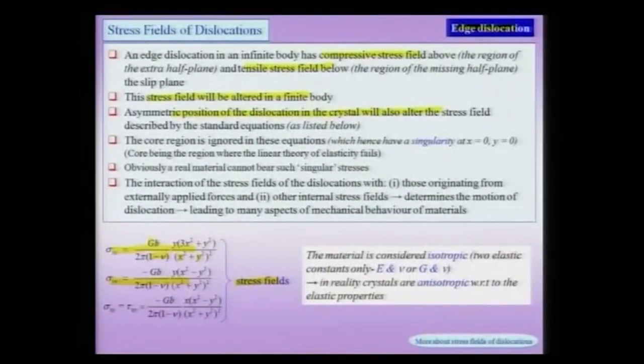We will see that when I put x equal to 0 and y equal to 0 in any of these equations, then the stress field will blow up. That means that obviously there is a singularity at the center of the dislocation line, and these equations are not valid in this region. Therefore, we have to understand that the validity of these equations is beyond the core region